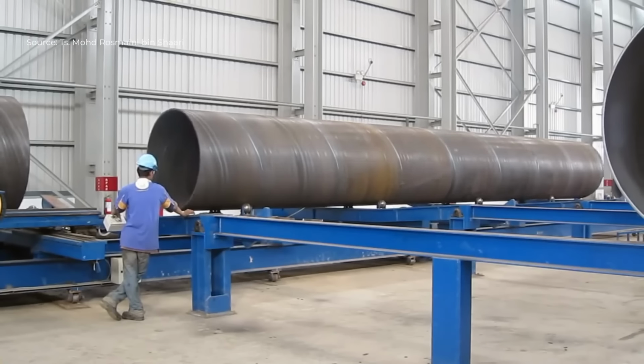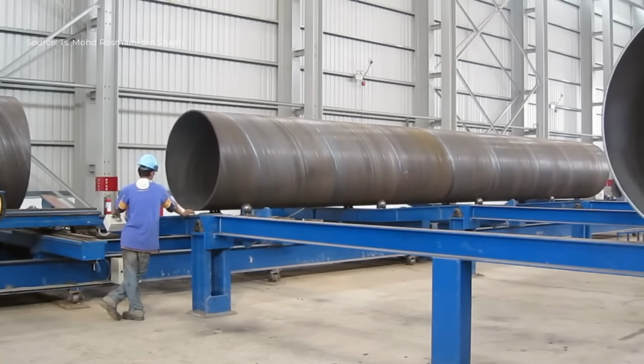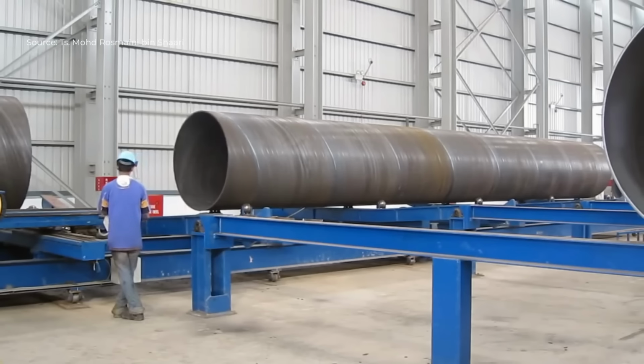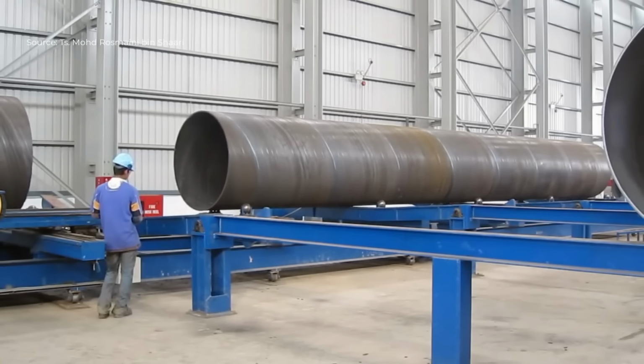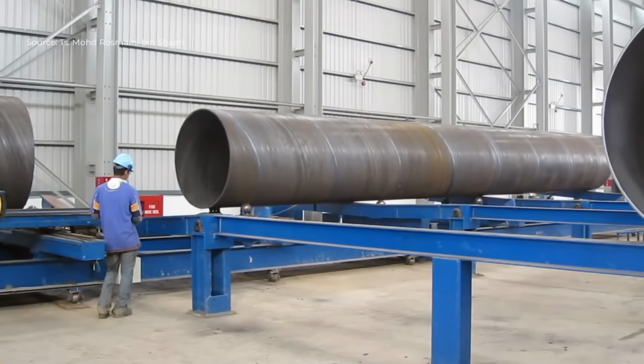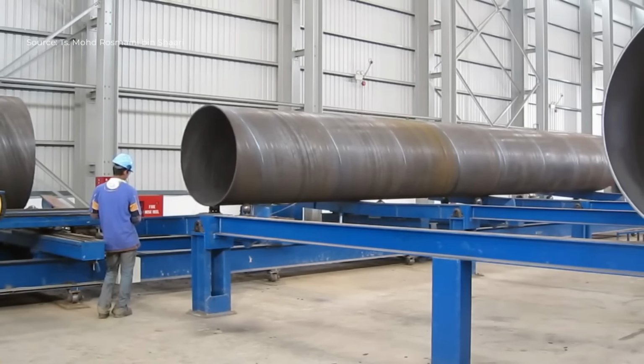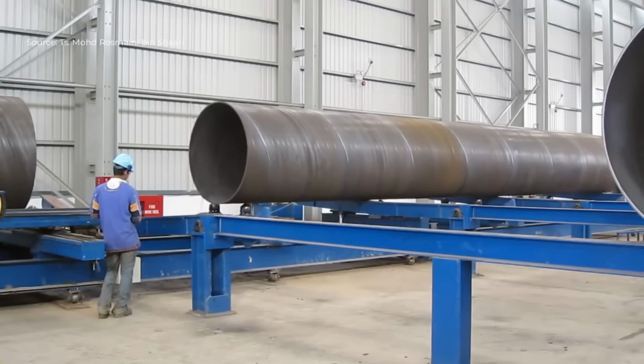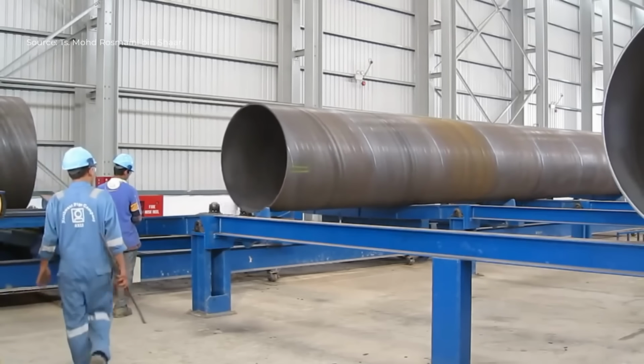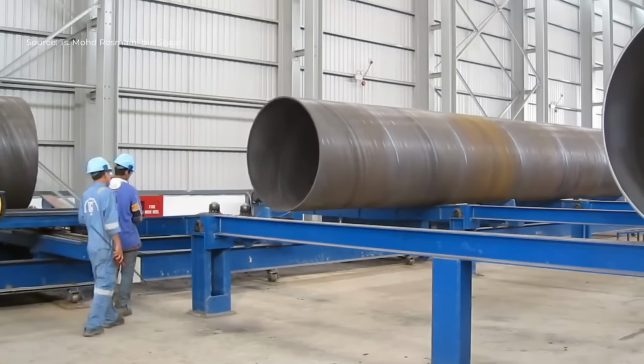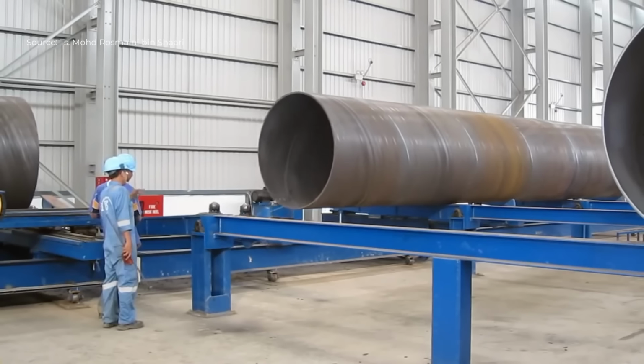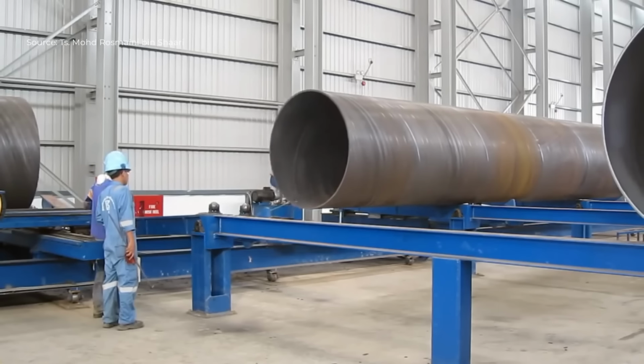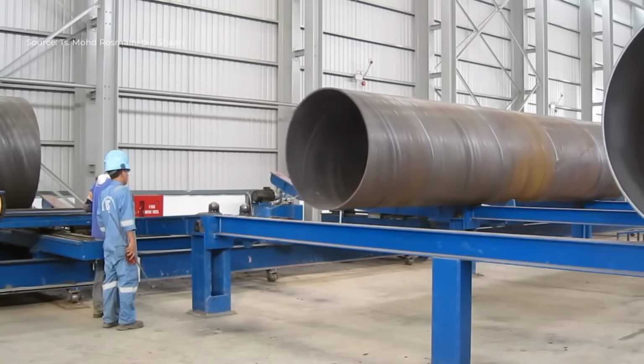Throughout both external and internal welding stages, parameters such as wire feed rate, welding current, arc voltage, and travel speed are continuously monitored and controlled automatically. This guarantees uniform weld geometry, high bonding strength, and excellent metallurgical properties. The combined external and internal submerged arc welding process results in a robust, continuous spiral weld seam capable of withstanding high pressure and demanding service conditions.